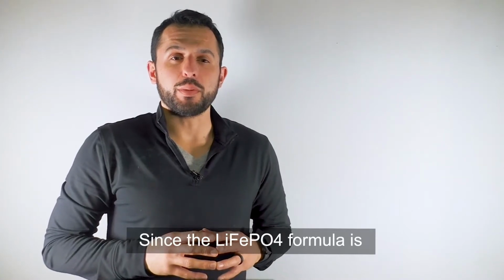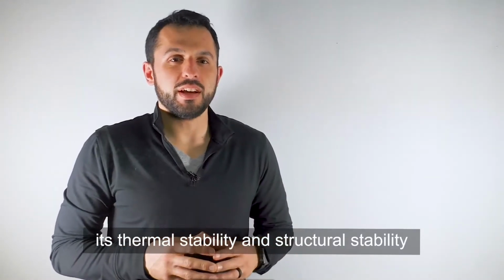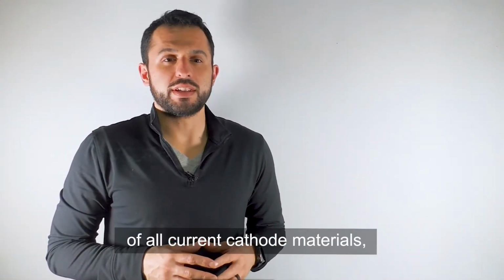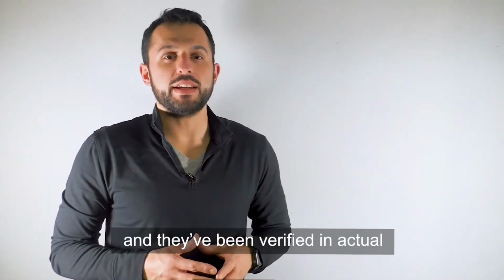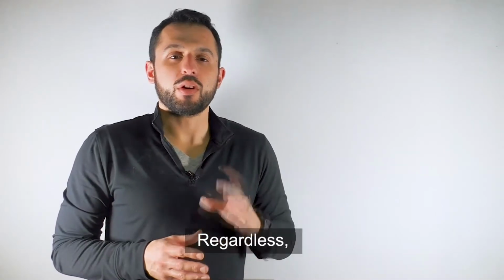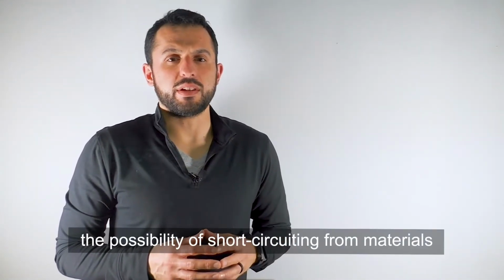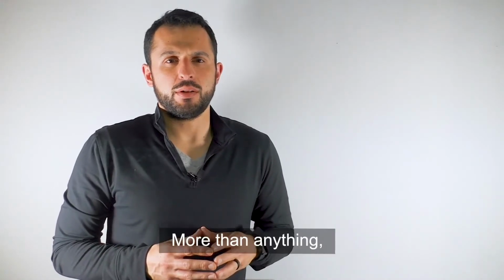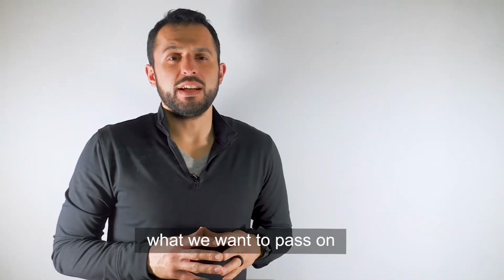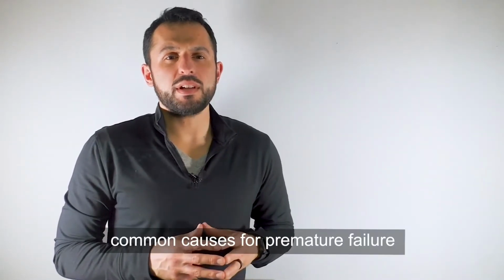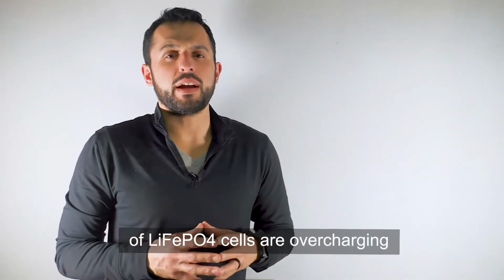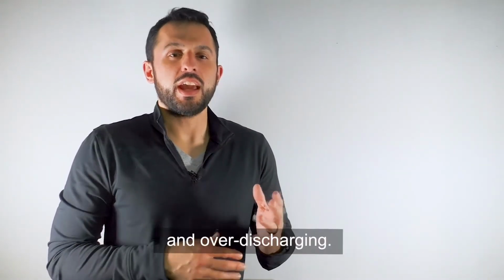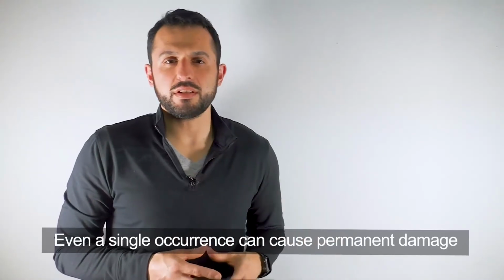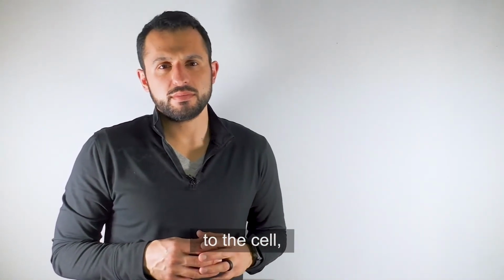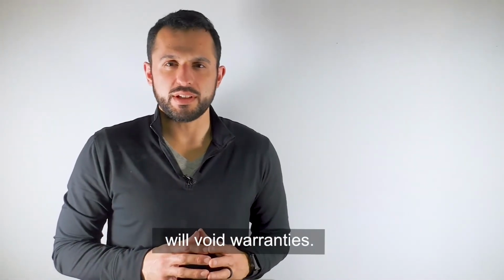Since the lithium iron phosphate formula is designed to be better thermodynamically, its thermal stability and structural stability are among the best of all current cathode materials, and they've been verified in actual safety performance tests. Regardless, the possibility of short-circuiting from materials and batteries is inherent. More than anything, what we want to pass on in this video is that the most common causes for premature failure of lithium iron phosphate cells are overcharging and over discharging. Even a single occurrence can cause permanent damage to the cell, and such misuse will void warranties.